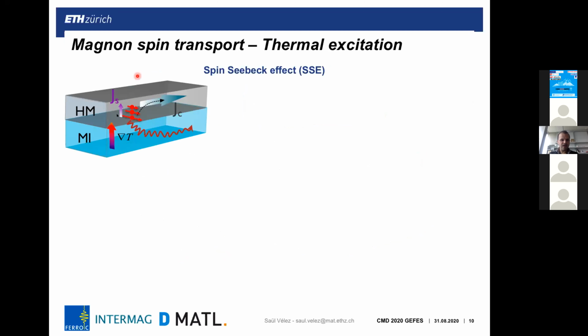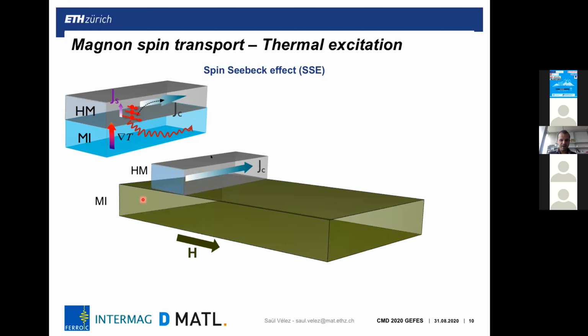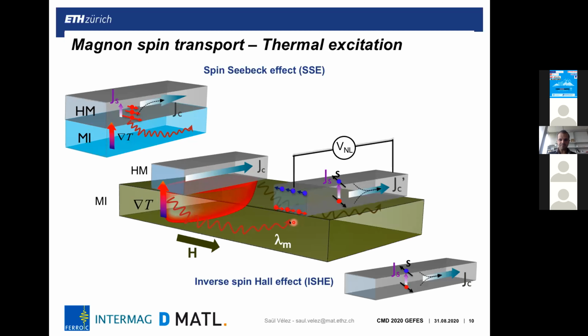So now we have to think also that we have a thermal gradient across an interface between a magnetic insulator and the heavy metal. So we can also drive spin currents to the heavy metal layer and magnon currents in the magnetic insulator. So now you forget about the spins. When you run a current, you also heat up your system, and this thermal gradient also generates a magnon current, and you can detect this magnon current by the same means by measuring the inverse spin Hall effect.